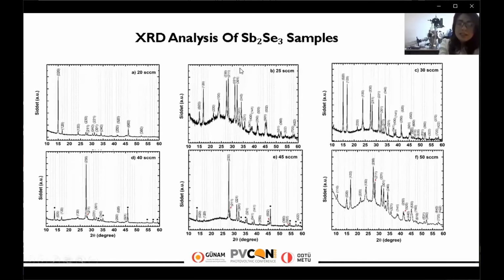To see these peaks in the XRD result, as I've previously told, we applied heat treatment to all 6 samples. If we didn't apply this heat treatment, we couldn't see these XRD peaks in the analysis. And here you see all peaks correspond to the antimony selenide characteristic peaks, but the peaks observed at 28.2 degrees and 31.2 degrees belong to the lattice planes 211 and 221 orientations.